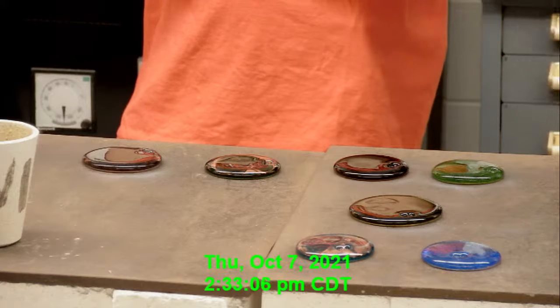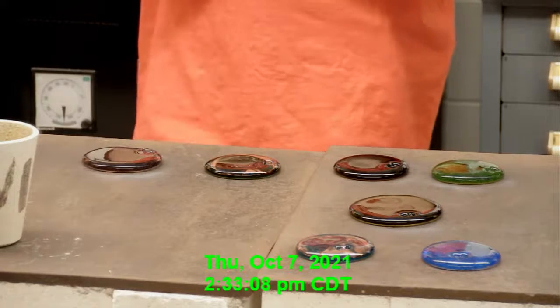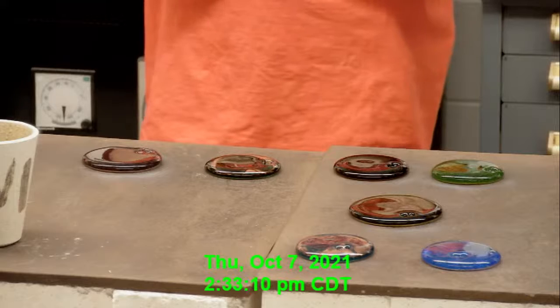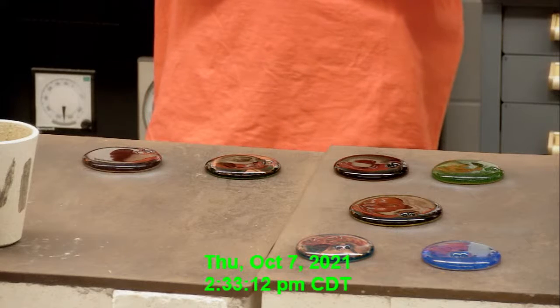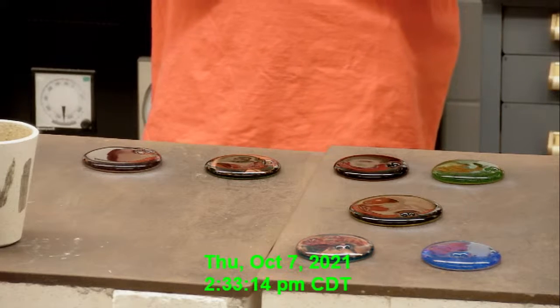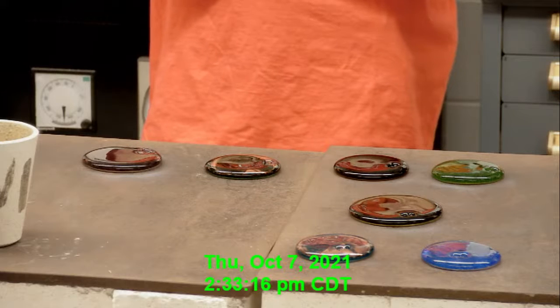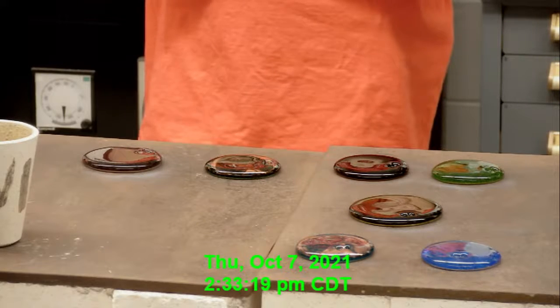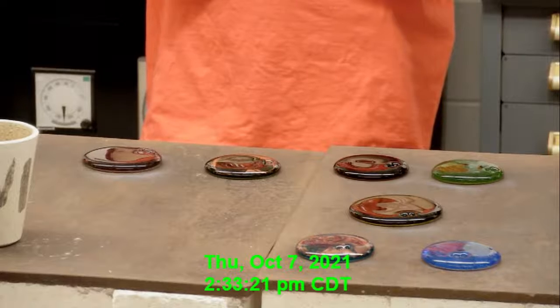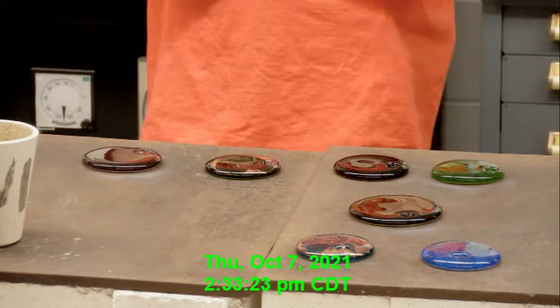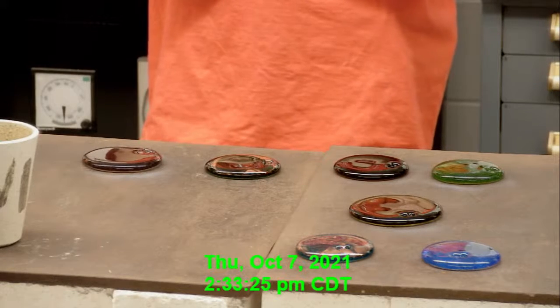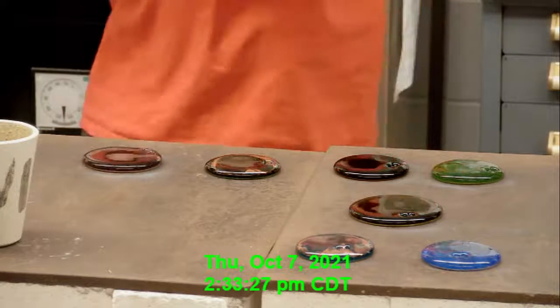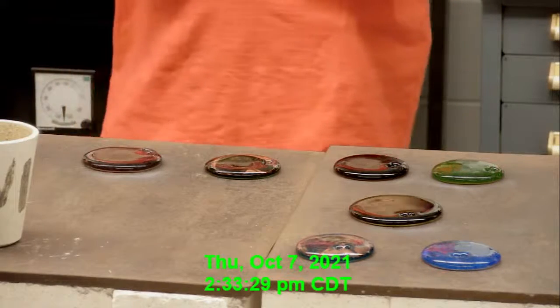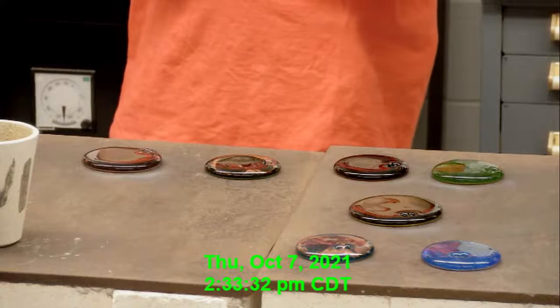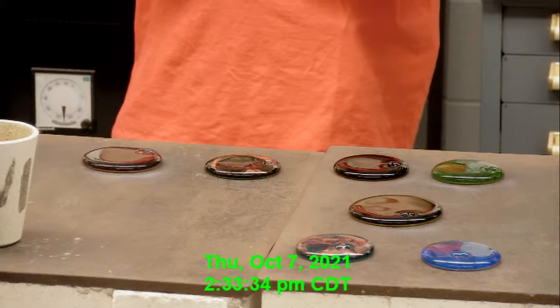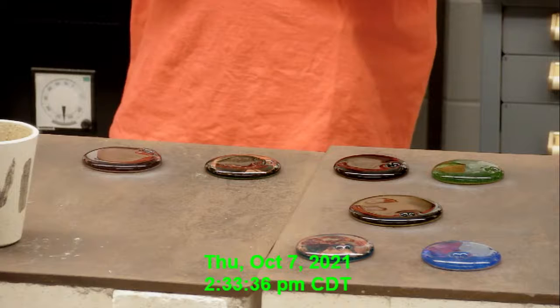But if you cross the polarizers and then put a piece of glass in between, you can see any shift in polarization caused by the glass. And I don't know if you can see it, but I can see it. You see these rainbow striations of color. The tightness of that pattern is directly proportional to how much internal stress there is in the glass. If you anneal the glass, it all goes to kind of like a gray color without these bands of color. But we'll be able to see lots of stress since this is surface quenched glass.